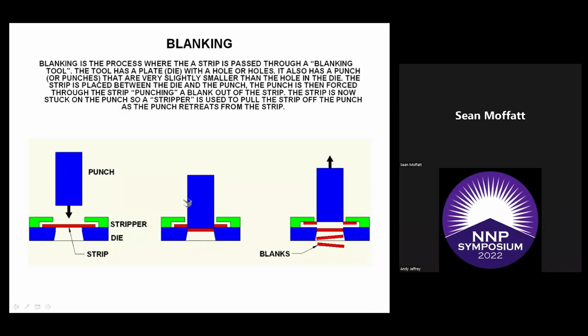So you can see right here we have our punch, and the strip is in between the punch and the die right here at the bottom. The punch comes down and knocks out a piece of the strip into the die, which is supposed to hold it there. Then as the punch retreats, the stripper pulls the strip off the punch. As you keep piling up blanks down here in the die, they all start falling out and the blanks come out of the press.